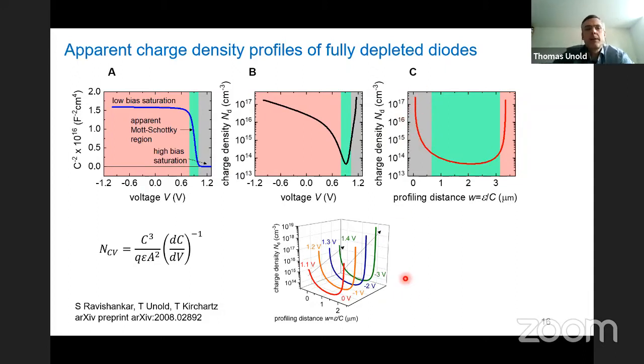And this was in the Science paper actually interpreted as a different amount of defects at the hole or the electron transport layer. And it's all over the literature, also for other materials, that these increases are interpreted as real charge carrier interface defects and so on. And so what we're showing here is that this can be, and usually it is, completely artifacts. One has to be very careful about this. I didn't mention, so this is on arXiv right now, a comment which was supposed to come out last Friday, I think, but maybe tomorrow it will come out.